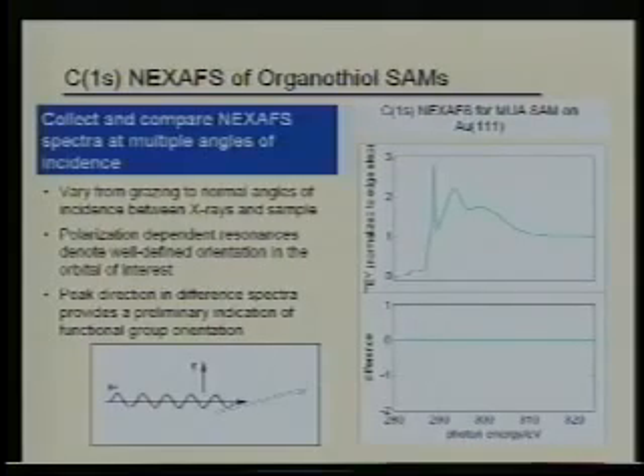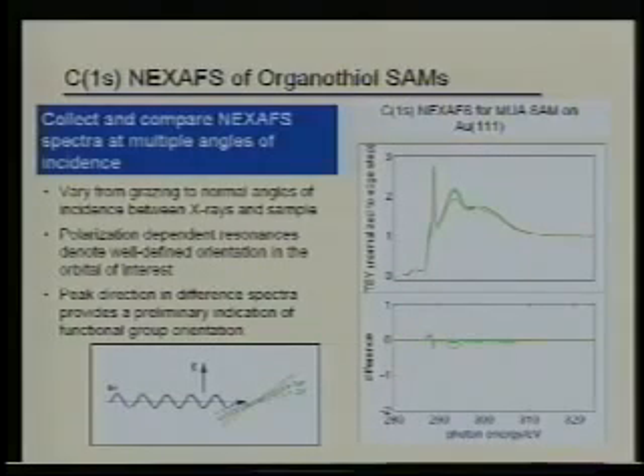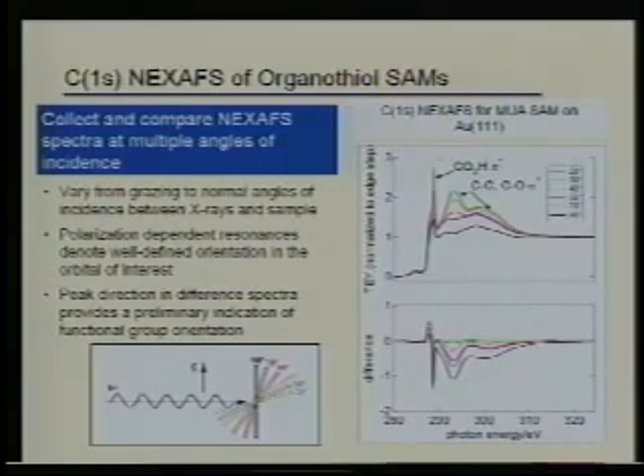So now we see if we change the angle of our sample in our X-ray beam, we see that these features change in real time. The polarization dependence changes these around, and the bottom graph is actually the difference spectra between the two. So from taking this information and the difference spectra, you can actually get, number one, if it shows this type of polarization, these films are usually ordered. Number two, you can actually get the tilt angle from these materials. And by looking at what the carboxylic acid group is doing, you can actually see the head group, what its orientation is doing. And we found that we can actually rotate the head group in real time by just changing the pH of our solution.